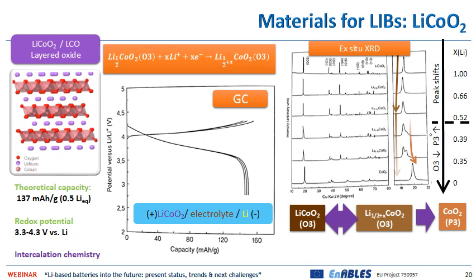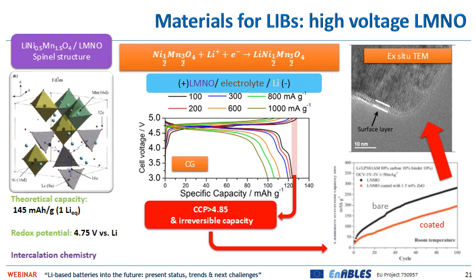Obviously, the control of the amount of lithium that is removed is very difficult, and in fact, cycle by cycle, irreversibilities occur, and part of the material converts to cobalt oxide, and at the end, the cell fails because the positive electrode is degraded. The current challenges in the research for the positive electrode materials are two.